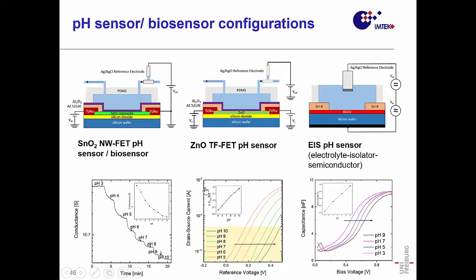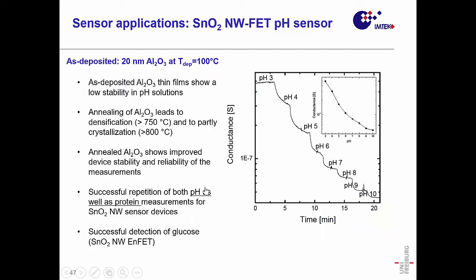Maybe I go to that image here. We use these tin oxide nanowires in an experiment which you see on the left-hand side as a biosensor. We have other things which we did partly as control experiments. So we started actually with thin films, ALD-grown thin films, in the middle. That is the middle one, and the other one is a kind of control experiment for the influence of the aluminum oxide, which we put over these nanowires.